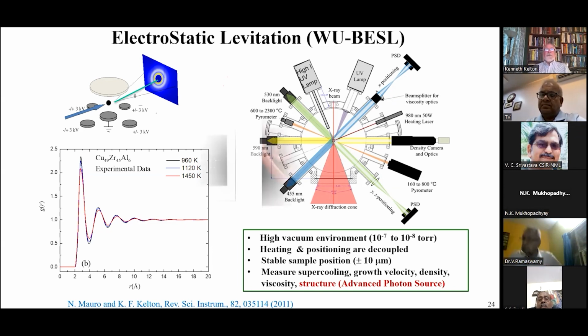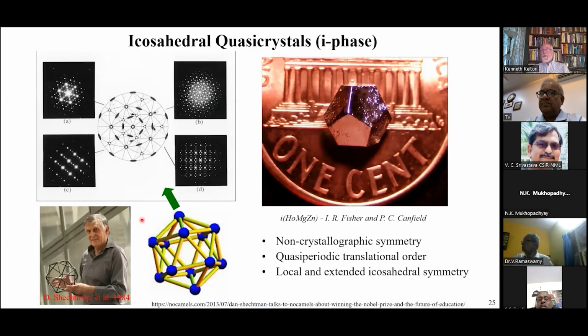The other thing I need to introduce is something that Ramachandra Rao would have been quite familiar with, which is quasicrystals. In 1984, Dan Shechtman discovered an interesting set of electron diffraction patterns that seemed to violate fundamental laws of crystallography, in particular this one. What he found was a diffraction pattern with 10 spots around a central spot. 10 is a multiple of 5, and it is well known that 5-fold symmetry is incompatible with translational periodicity. This led to an entirely new field, the field of quasicrystals, and Dan was given the Nobel Prize in chemistry for it in 2011.